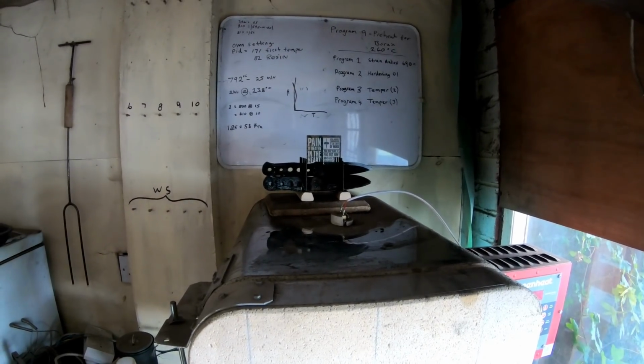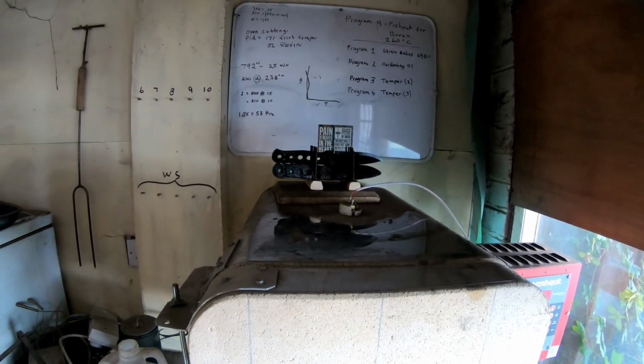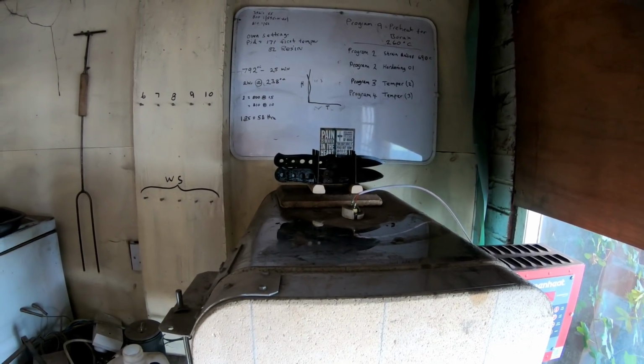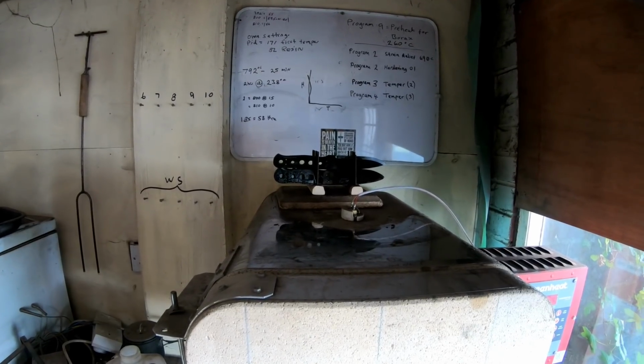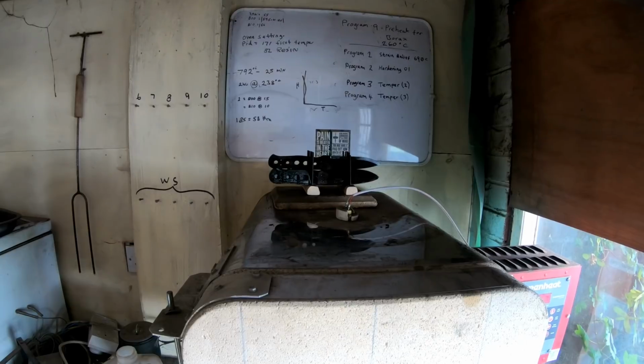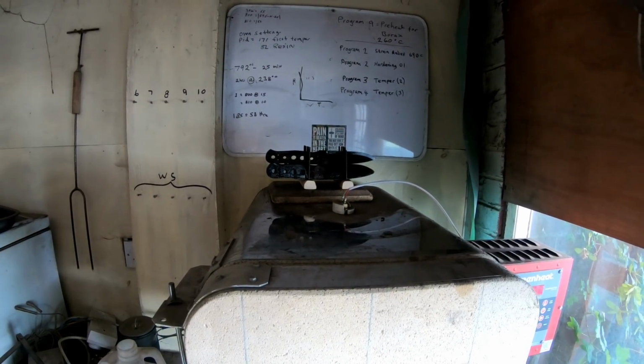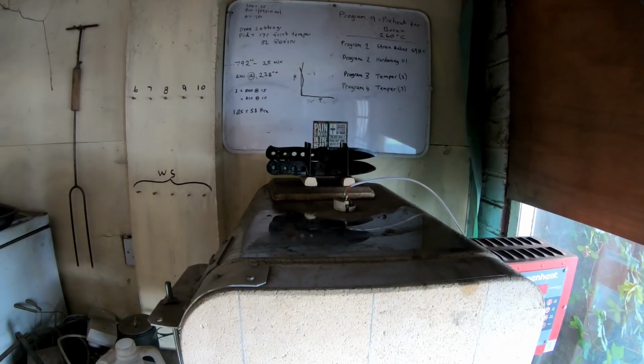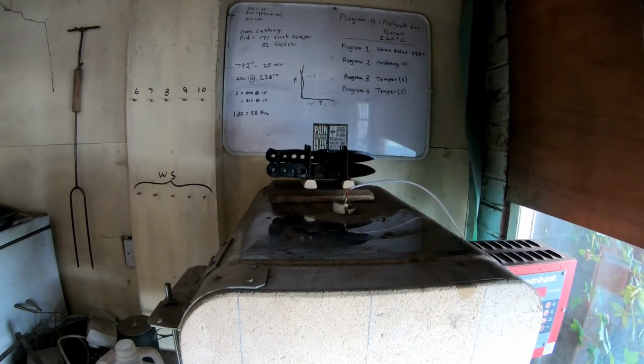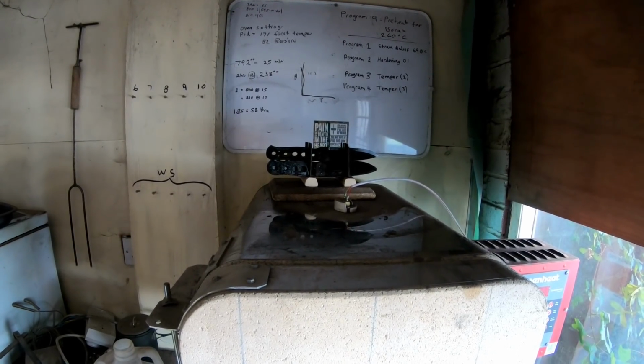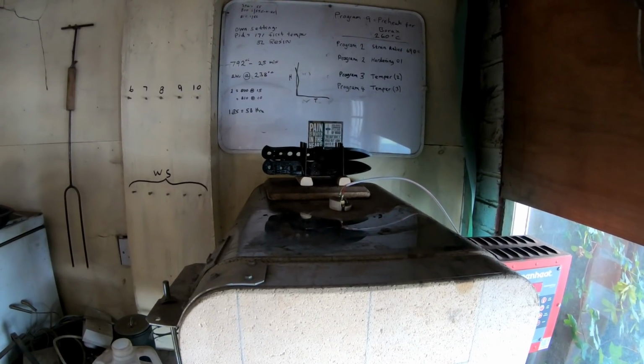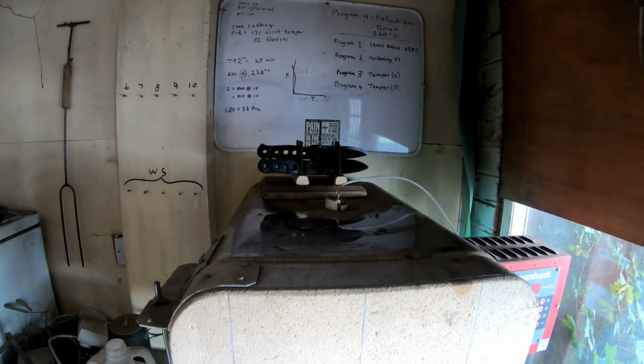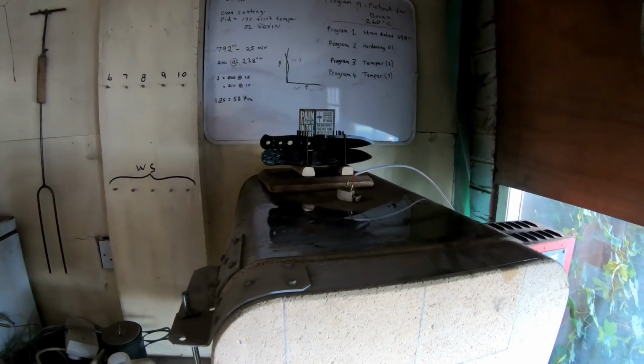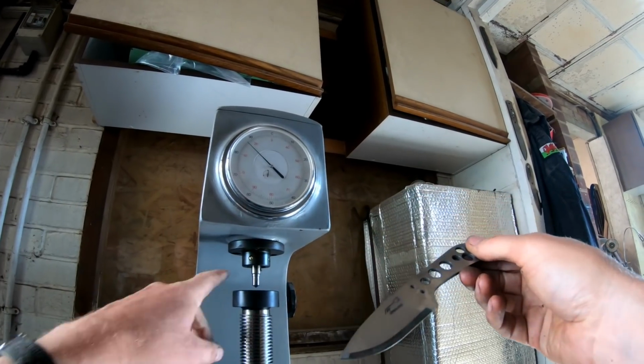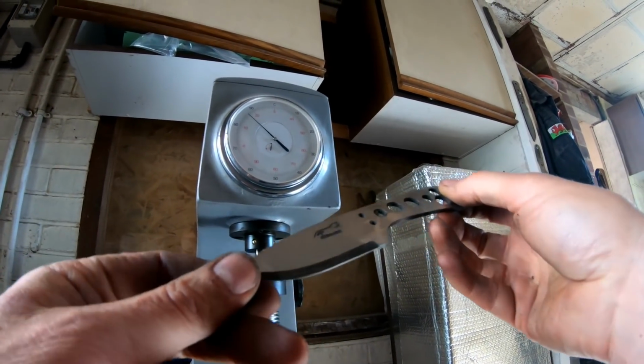I think it's really important to mention that I like to leave my knives to rest a little bit after I've quenched them, because the quenching process is just that, a process. It takes a little while for the blades to convert fully. For the first minute or so after you've quenched a knife, you can still bend it. But if you leave it for say 2 or 3 minutes and then try and bend it, the chances are it will snap. So the conversion from austenite to martensite doesn't happen instantaneously. The blades have really cleaned up nicely. I'm going to test them for full hardness now.